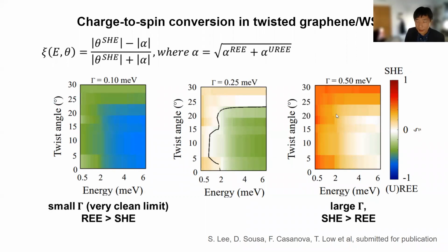One can understand this quite intuitively, because the Rashba Edelstein, remember, is a Fermi surface effect. If this is a Fermi surface effect, then it should be most prominent when the temperature is low, and also when the disorder is very small, which is what we observe here. But the spin Hall effect is a Fermi sea effect, so it's not so sensitive to the disorder, which is why it survives at very large disorder or very large temperature.